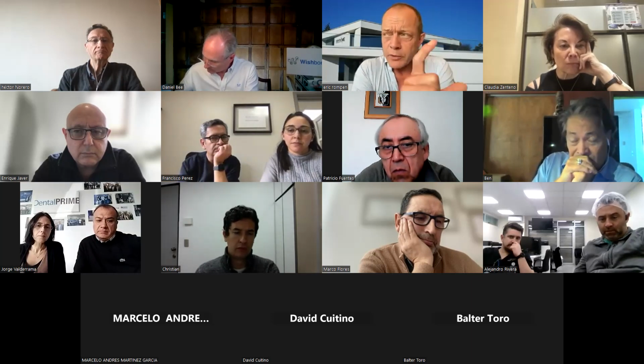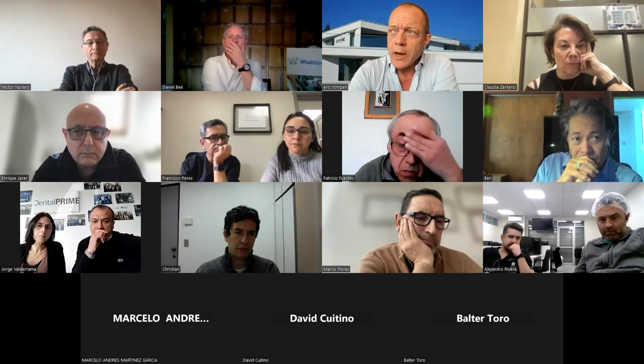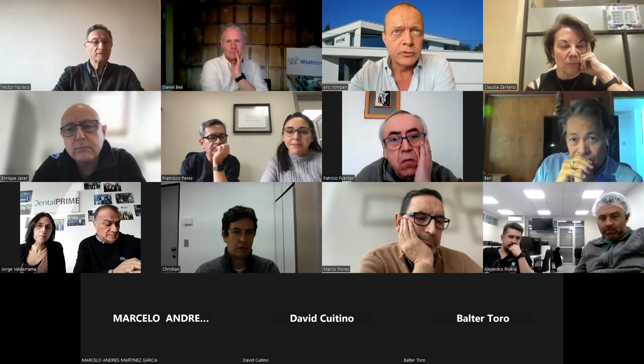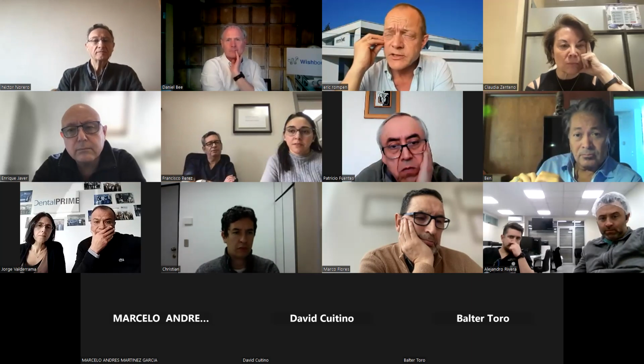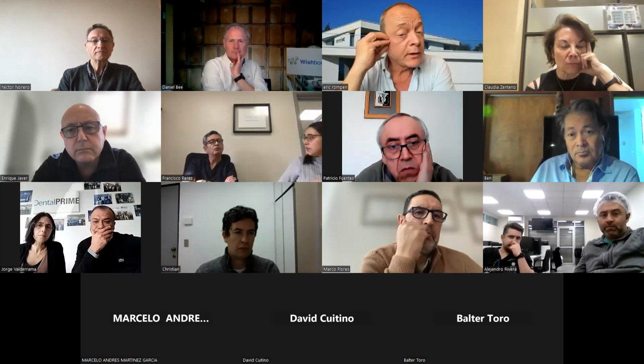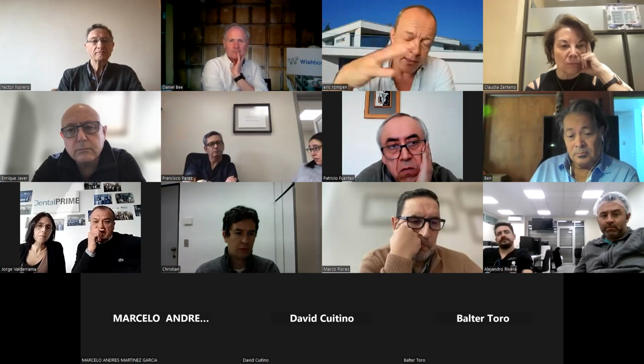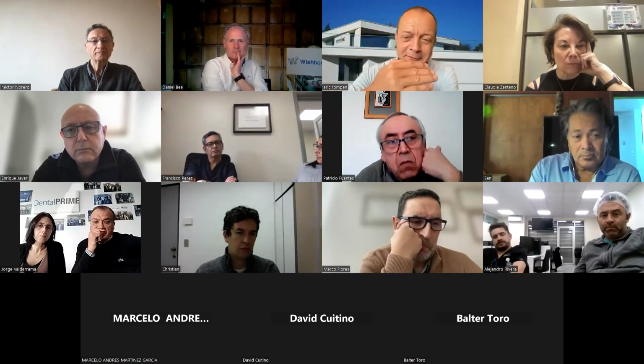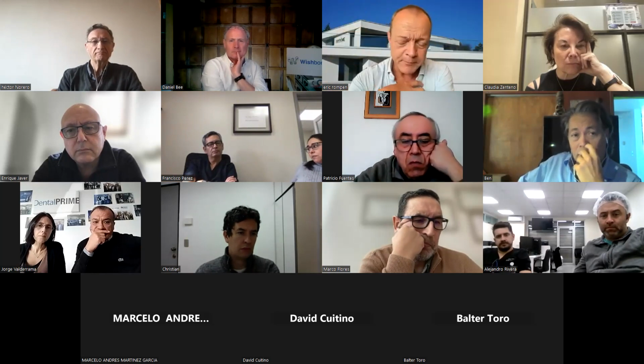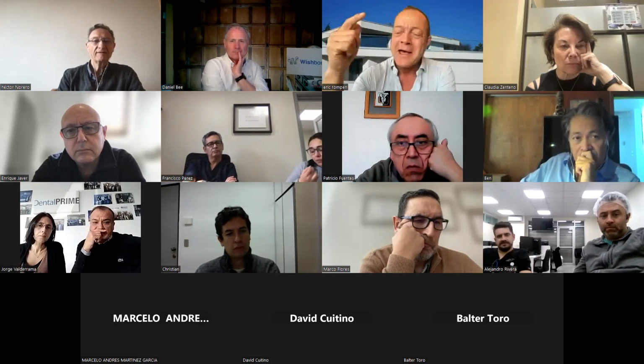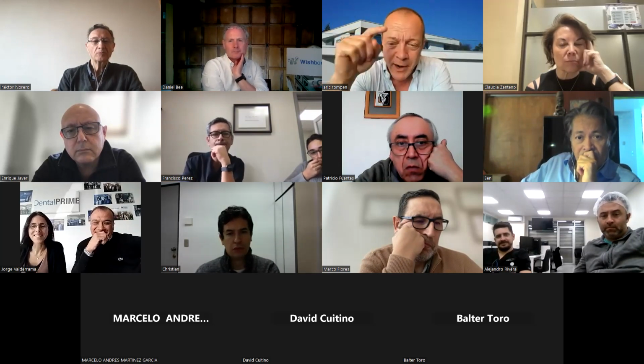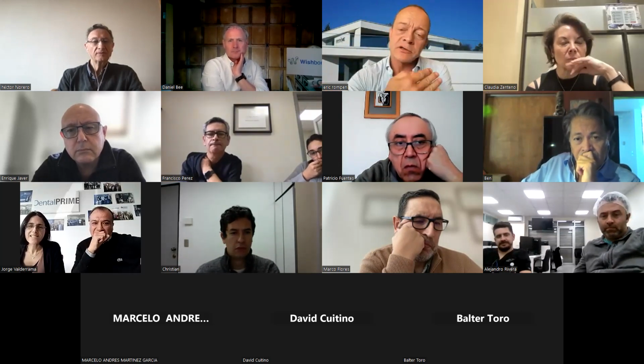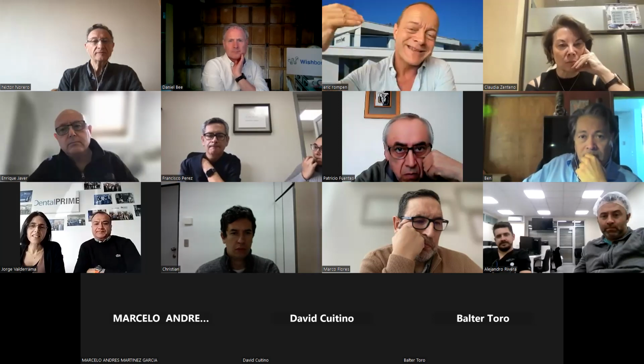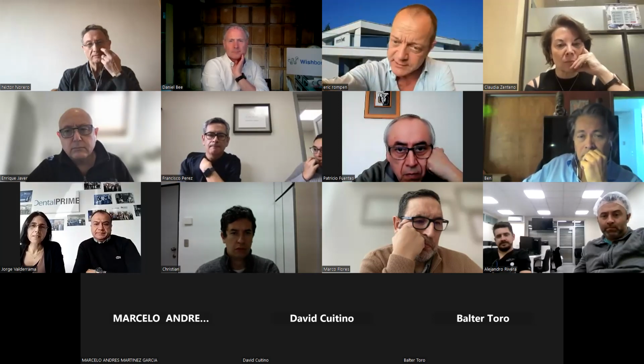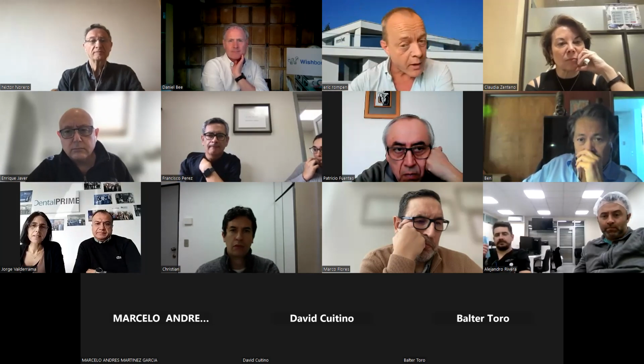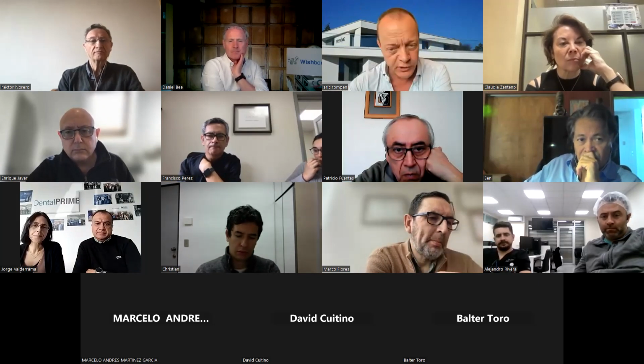What I could also add is that I didn't show that in this presentation because the goal is not to criticize other materials, but there are some papers showing very clearly that with Bio-Oss, and I still believe that in Europe on the market, the Bio-Oss is really a gold standard for me, but we are better than that. With the Bio-Oss, we have a very high osteoconductivity. We have a very good quality of the bone at the end of the regenerative process, but the Bio-Oss will slightly slow down the bone regeneration.